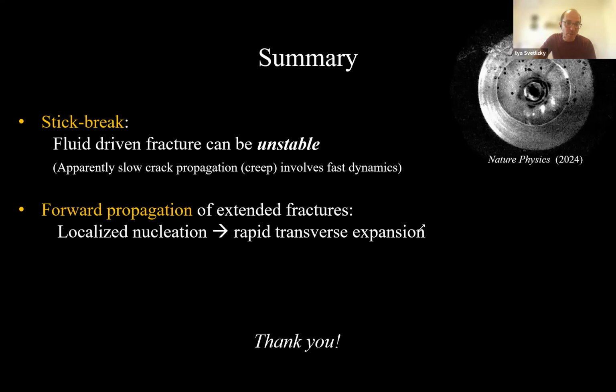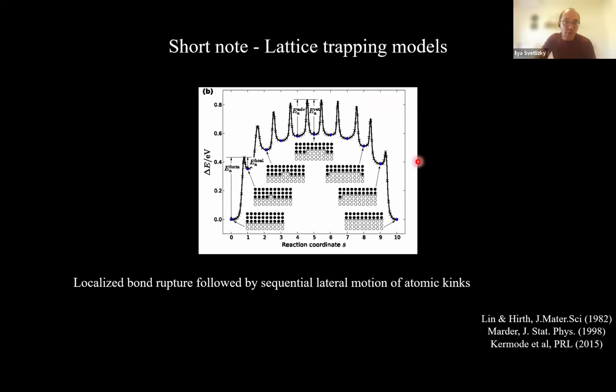I totally agree. I hope our results extend beyond fluid-driven fracture. As I said, I'm not very familiar with stress corrosion cracking, but from what you described, if the crystallinity of the material is important, these are models that try to explain why creeping cracks in single crystals can propagate very, very slowly. The argument was that you jump atom by atom over time. I think it's very similar. I'm not aware of direct visualization of this process, unless, as you say, people measure acoustic emission. This is true, you are absolutely right.